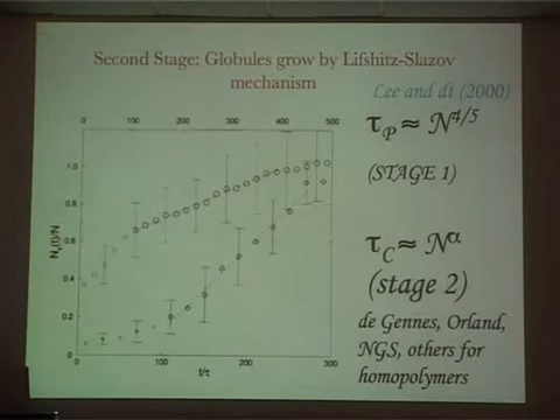The mechanism, in fact, occurs in two stages. The first stage is to form this very large cluster, and if you want, you can again, to please my host Sri, call it a nucleation, and then these clusters have to be connected and finally engulfed. And the nucleation we predicted using theory: the time scale scales as n to the 4/5.